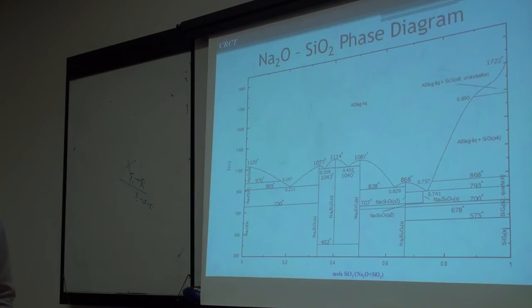You can actually realize this, because you can suppress the formation of silica since it's extremely viscous. In fact, if you cool this material, it forms a glass. To get the crystalline form, you've got to wait a long, long time. So if you cool it down, you will in fact see the two-liquid miscibility region down in the glass region. It's a supercooled liquid, very viscous at that point.